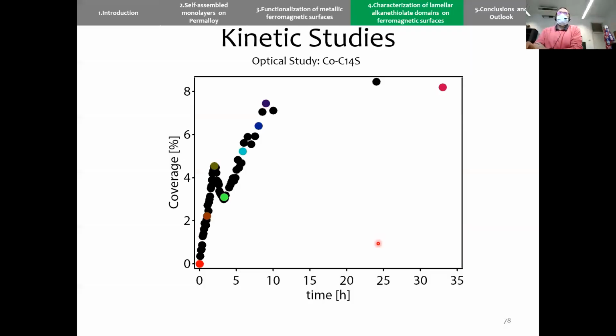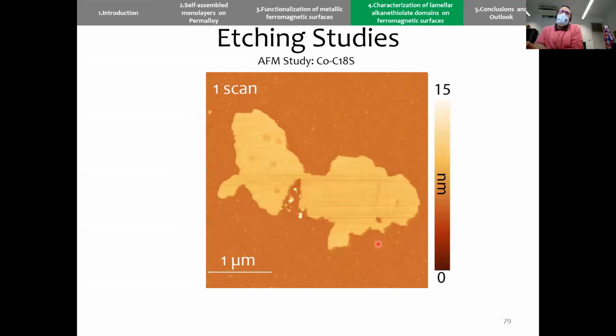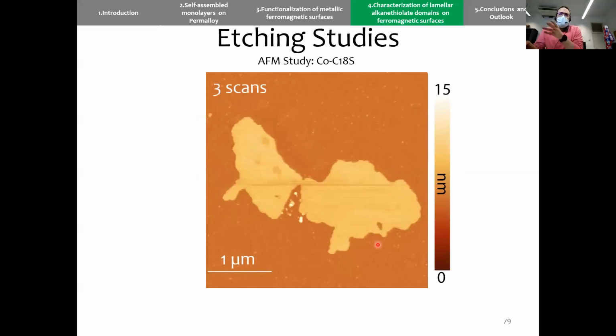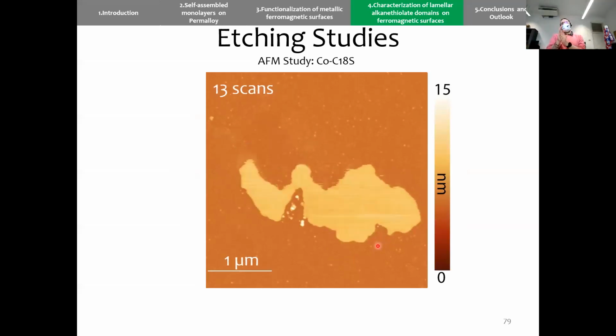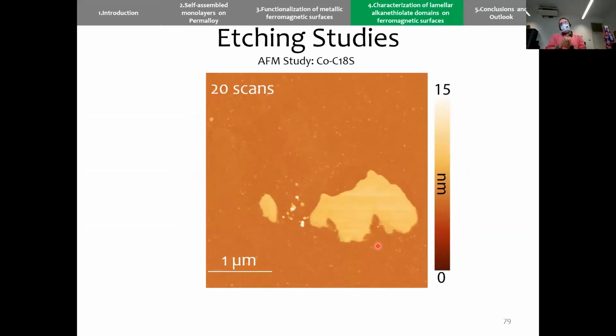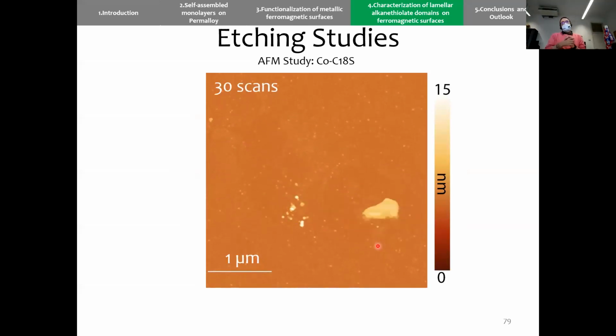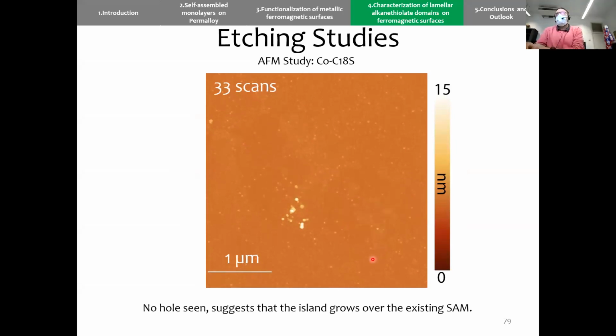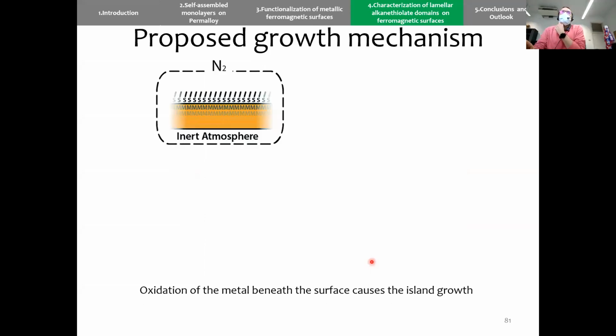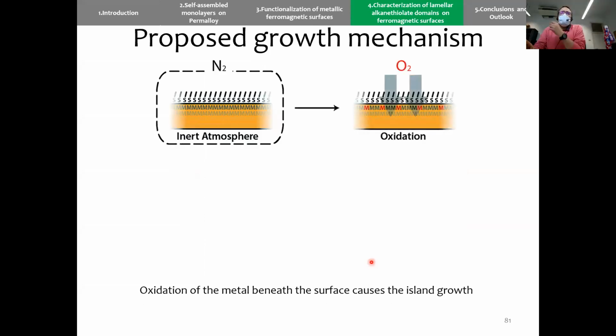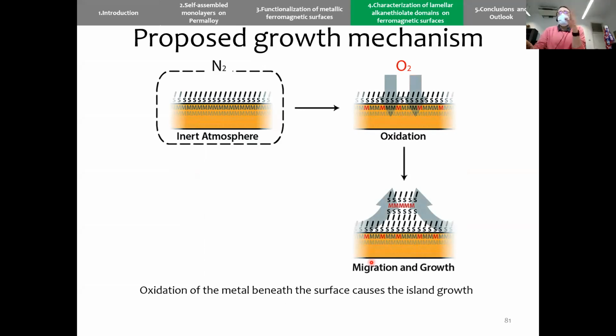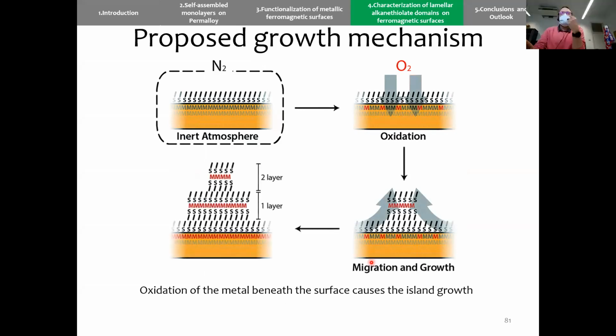It was very puzzling for us. And also, if you look very close with the AFM, you could etch them layer by layer. So it was a tricky material to characterize, and so this is our mechanism. An initial oxidation causes the migration and growth, and that's why we get a layered structure.